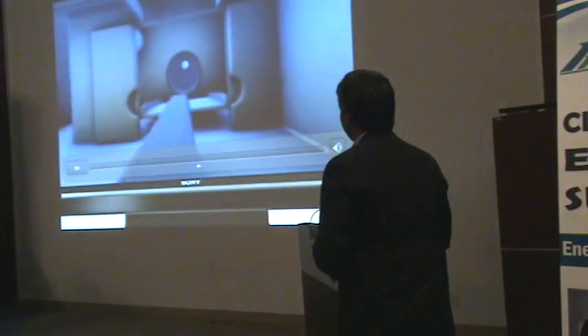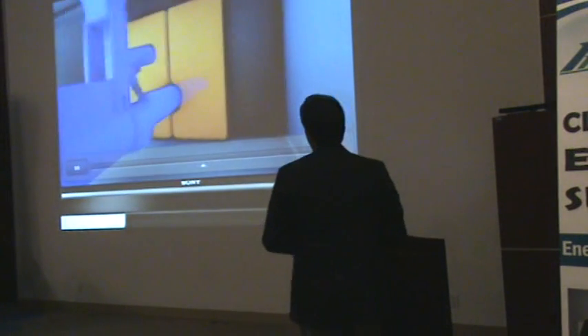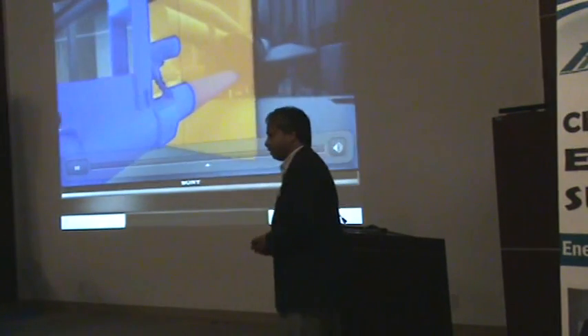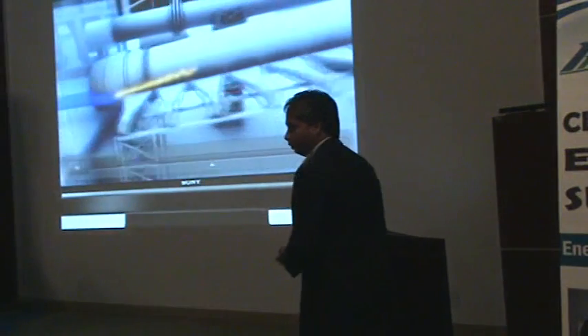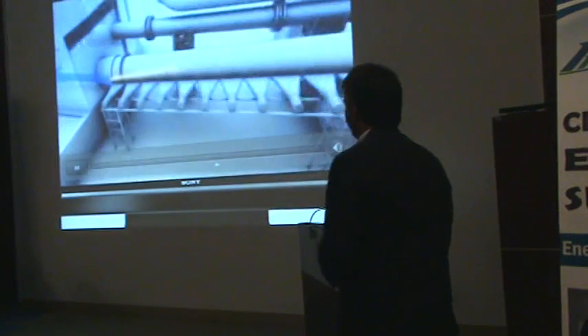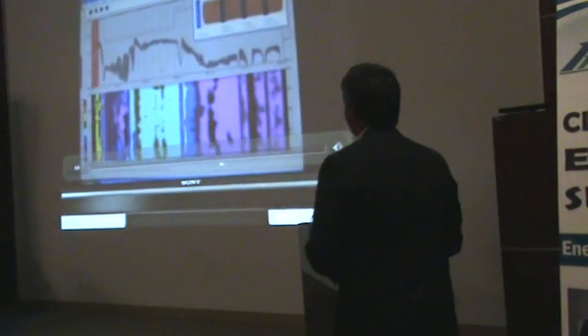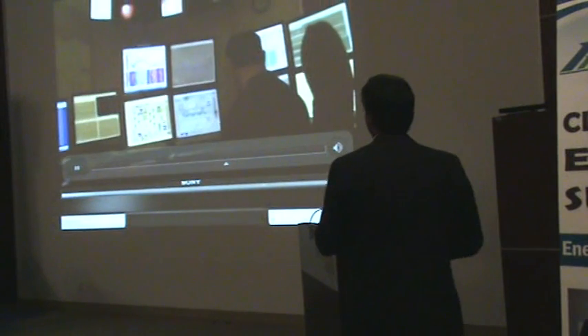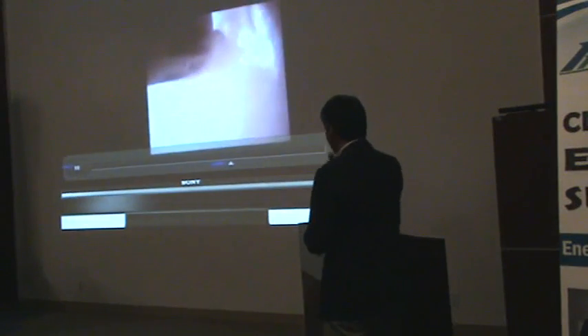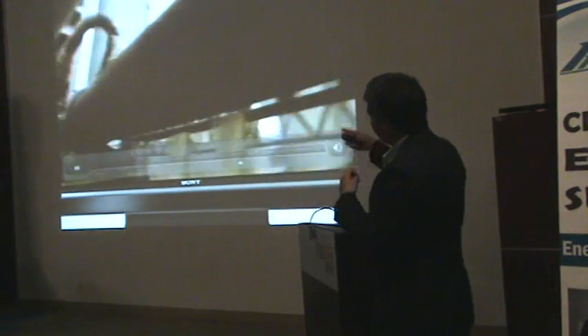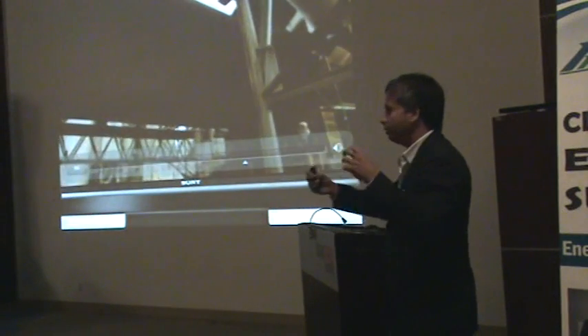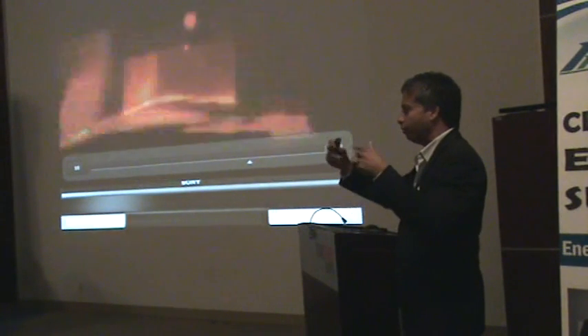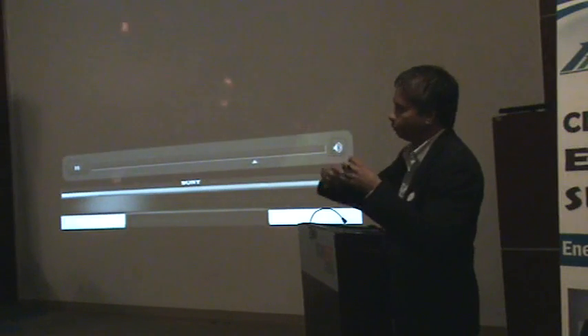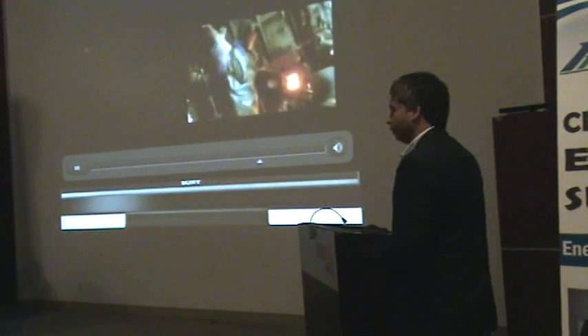We get the heat from burning fossil fuels. We burn a lot of fossil fuels. The Bowmanville plant here burns about 30 tons an hour of petroleum coke. That's a lot of energy. 92% of the energy consumed on a gigajoule basis is coming from fossil fuels and used directly. So that's a shot inside the kiln from the thermal camera. If you think of that kiln, it's kind of like taking a paper towel tube, putting sugar in one end, putting it on a little angle and rotating it, and then the sugar will move from one end to the other. That's all that we're doing, but we're doing it on a ginormous scale.